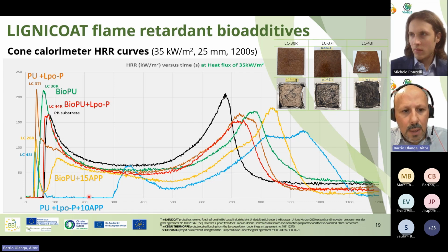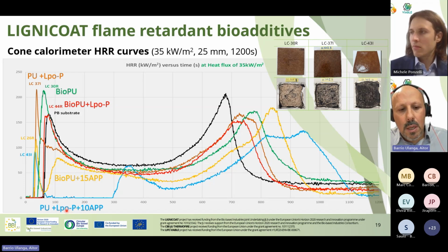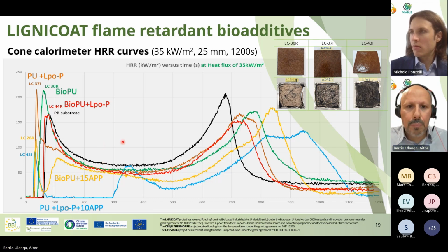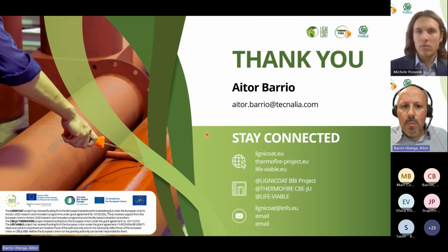We have reduced the combustion of the material a lot, by more than 200 seconds, and it starts the combustion, but with a very low heat and very low total heat release during the combustion. So this is a good result. We are reducing 5% of APP using a smaller amount of a bio-based lignin, phosphorylated lignin. So this is all from my part.